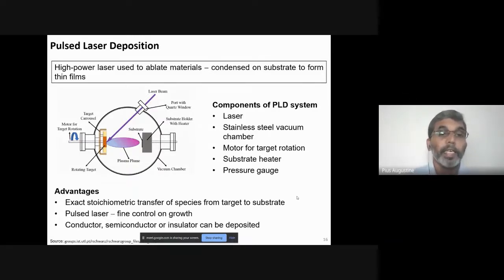That is having many elements inside, components, yttrium barium copper oxide. My PhD work was on PMN-PT, a material system: lead, magnesium, niobate, lead, titanate. So there is lead, magnesium, niobium, titanium, oxygen. So many are there. When such a material is to be transferred to get this perfect stoichiometry, normally many thin film processing techniques may not support. So that's why pulsed laser deposition came in.